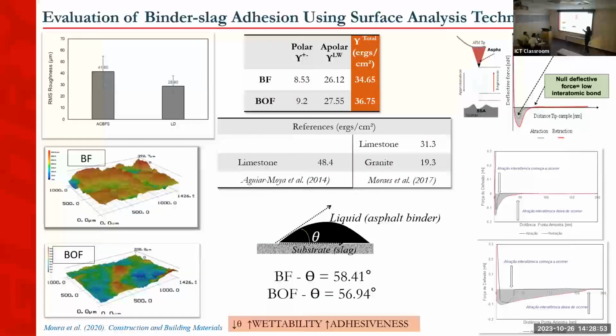The AIMS results I didn't plot here, but they were very similar. So the difference in angularity could not explain why one slag adhered better to the binder than the other. From the surface measurements, we saw that the BF slag has a higher roughness than BOF, which could result in a better adhesion, but that was not what we observed. The values were not too high. Compared with the standard deviation, we can say that this is not the reason why one slag is performing better than the other.